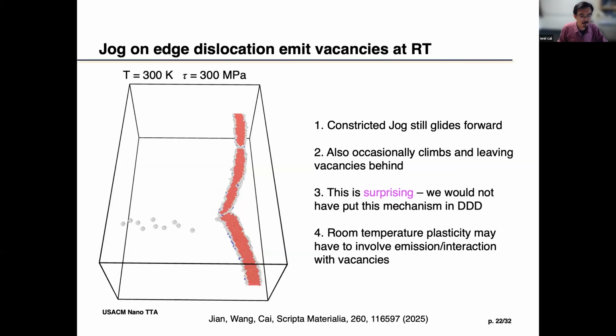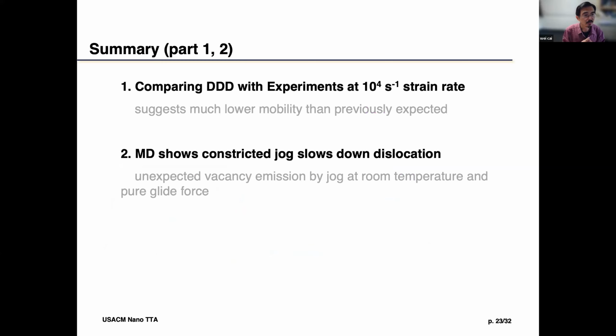So we cannot avoid the jogs. Now the jogs are saying that we may not be able to avoid the vacancies. So crystal plasticity may turn out to be more complicated than we thought. So this is just a quick summary of the part that we discussed. Basically we enabled our first ever one-to-one comparison between DD simulation and experiments at the high strain rate, 10 to the fourth. That work led us to wonder why the mobility law has to be much smaller than what people believed. That led us to study the jogs by MD simulations, and we found that jogs indeed lower the mobility of dislocations. And then there's a surprising behavior, that the jogs also emit vacancies.